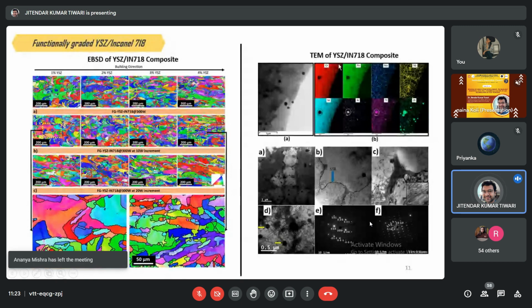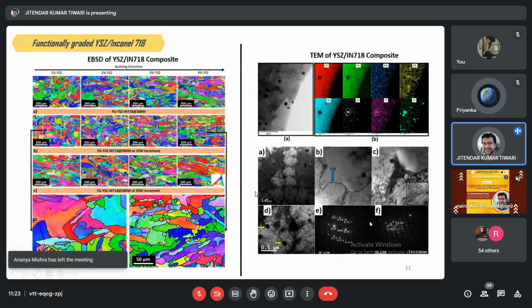There are some transmission electron microscopy results. So in TEM, as you can see, these spots. We have investigated these spots, and there is some proof of formation of this, the unwanted phase. So we must avoid the formation of these phases, because it degrades the property of the material.